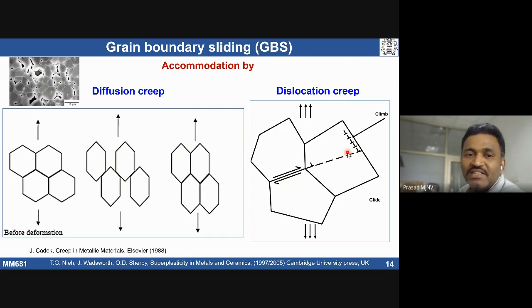At high temperatures, negligible strain hardening will be there. In both the cases, materials are going to show large elongations at low stresses. But how is that large amount of strain coming? Because of grain boundary sliding. That's the dominant mechanism, but it has to be accommodated with some other mechanism. Otherwise, it's going to leave you cavities.